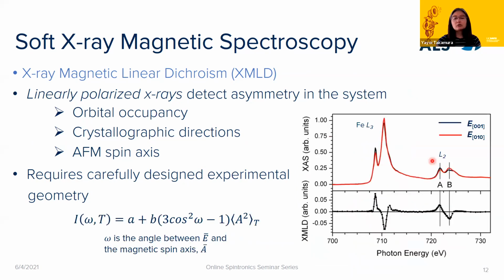As an example of what the spectrum might look like, again, this is for the iron in LSFO. The line shape tells us that we have a mixture of iron 3+ and 4+ valence states. Then we see that both peaks break up into A and B peaks, which is indicative that it is an oxide and not metallic iron. And you can see that we get these plus-minus features for both the L3 and the L2 edges when we do the different spectra. Again, each source of linear dichroism, whether it's orbital occupancy, crystallographic effects, or the spin axis, will have a characteristic line shape.